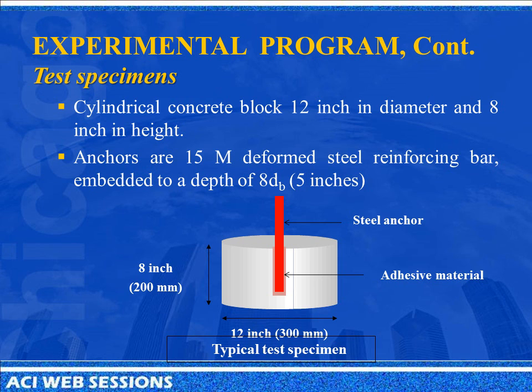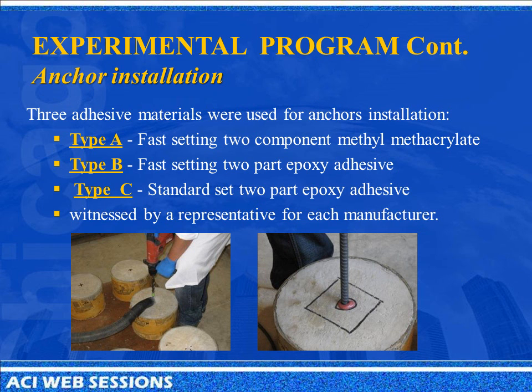A typical specimen, like you see here, is a cylindrical concrete block, 12 inches in diameter, 8 inches in height. All anchors were 15M deformed steel bars embedded to a depth of 8 bar diameters, or 5 inches, approximately 125 millimeters. Of the three types that we used, type A is a fast-setting two-component methacrylate base. Type B is a fast-setting two-part epoxy adhesive, and type C is a standard-set two-part epoxy adhesive.